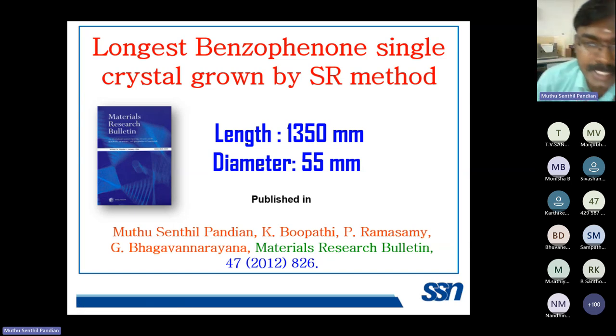So based on our experience in this unidirectional crystallization method, we attempted to grow the world's longest benzophenone crystal, and we have successfully grown this large size, 135 centimeter length and 5.5 centimeter diameter crystal. In fact, we initiated this work in 2007 when I joined as a PhD student, and we successfully completed this work in 2011, and reported it in 2012 with the help of Professor G. Bhavanarayana, who worked at the CSIR National Physical Laboratory in New Delhi. With the help of Professor G. Bhavanarayana, we completed it and reported it in this journal.